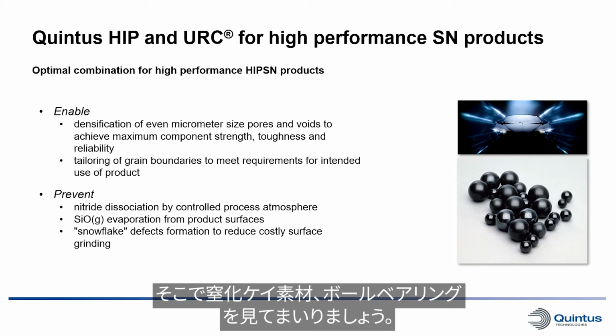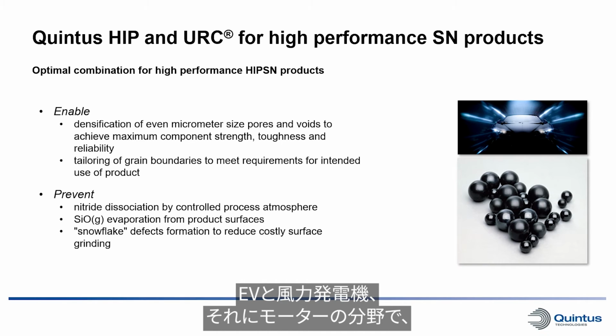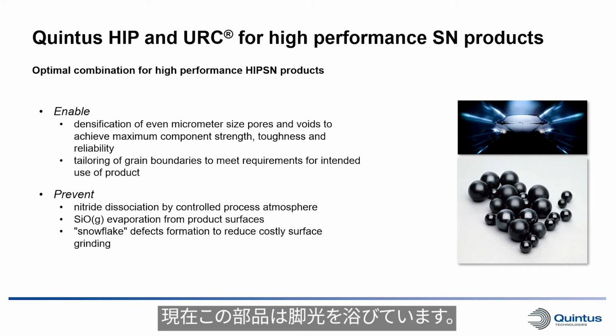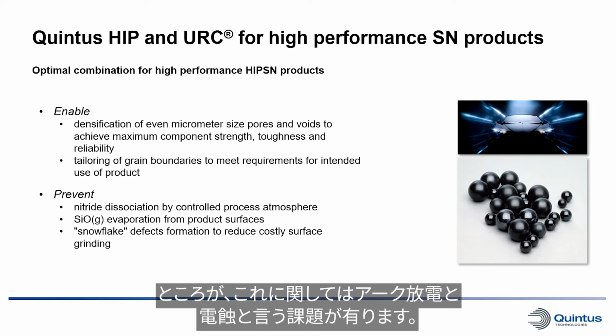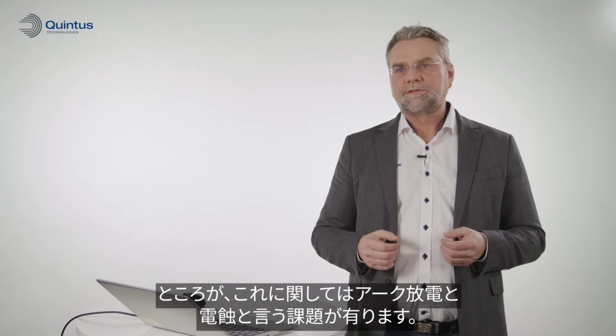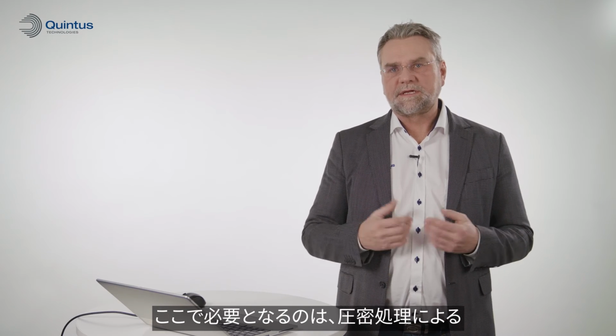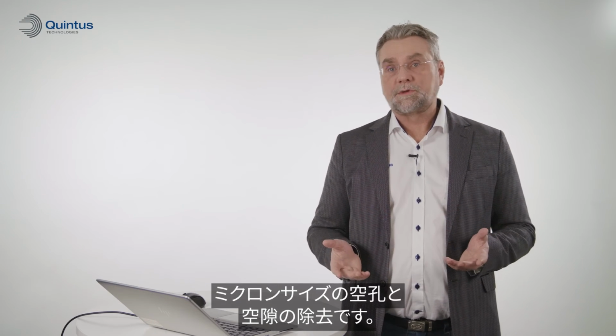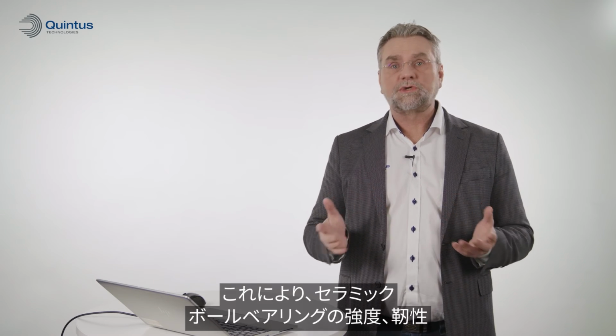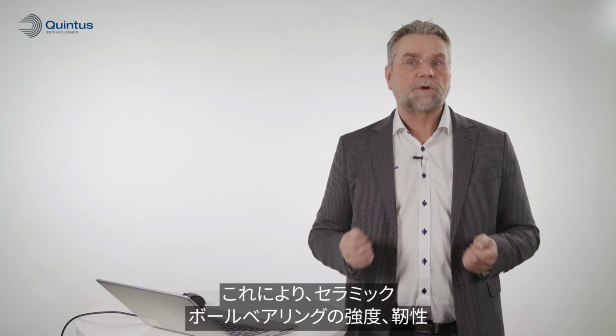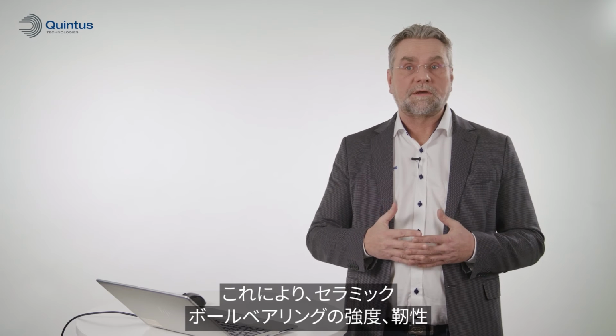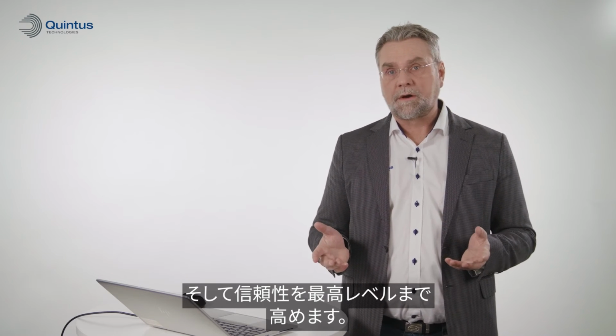So, of course, we need to look into silicon nitride and ball bearings, since that is booming at the moment with EVs and windmills and any electric motors where there is an issue with electrical arcing and electrical corrosion. So, what we need to enable is the densification of also micrometer-sized pores and voids to make sure that we have the best possible strength, toughness and reliability of the ceramic ball bearings.